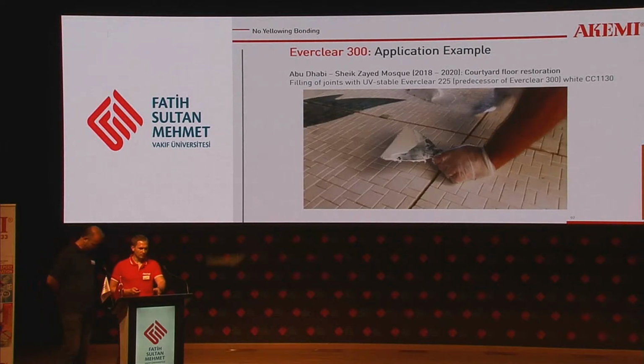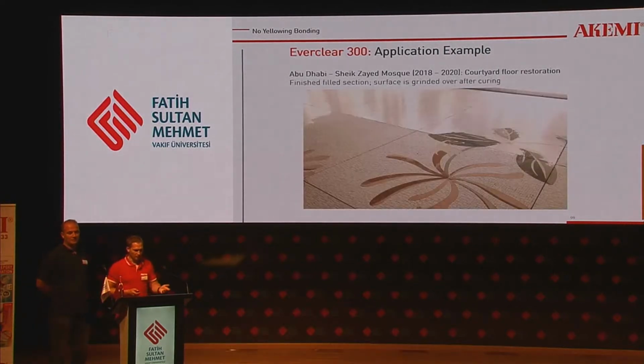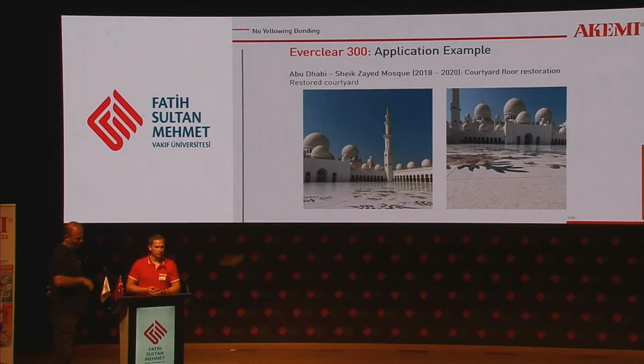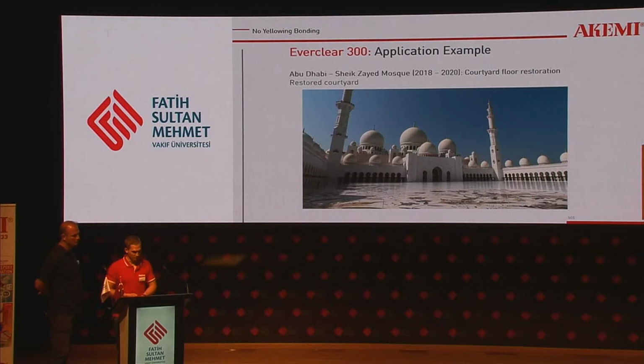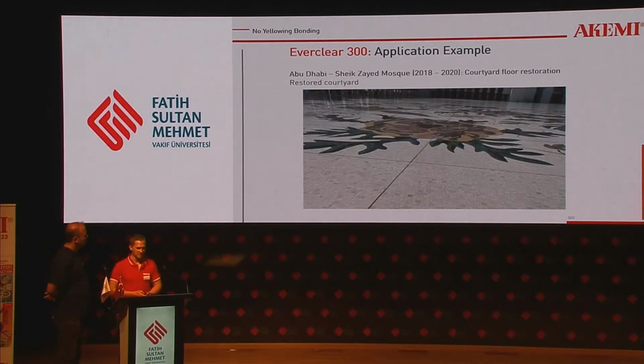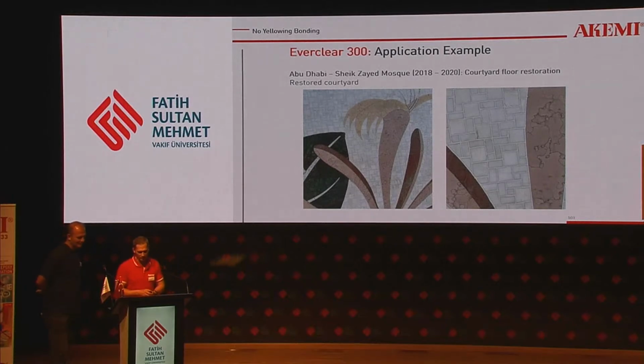And then at nighttime, after the grinding and the drilling, they filled in the joints with big spatulas. And after the curing was done, so the curing had to be very fast, around 2 or 3 hours later, they could already grind and polish the surface. And now, since 2020, the Sheikh Zayed Mosque is beautiful again. Also the flooring. And it's a very beautiful building. I hope I can visit it sometime, because this was done by my colleague. But here you can see all those joints are now very beautiful, and you can see the mosaic again in a very, very good condition.